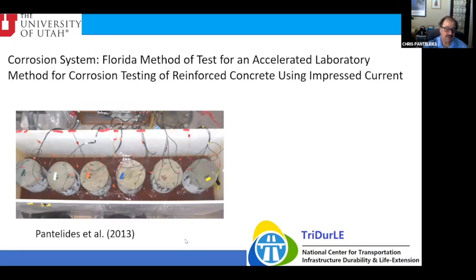So the intent of this first study was actually to see the corrosion performance of the all fiberglass columns, the hybrid columns with the fiberglass spiral, and the all steel columns. So we used the Florida method of test for accelerated corrosion using impressed current. And you can see here, half of the column is immersed in water, the other half is in the air, and we're passing direct current.